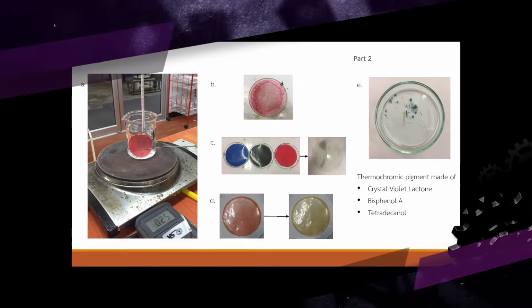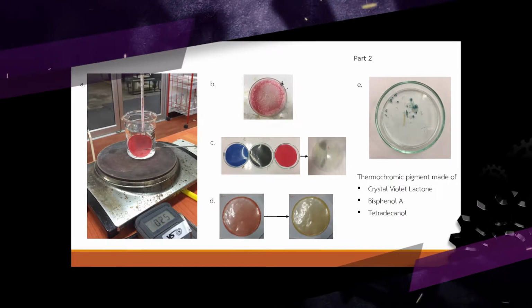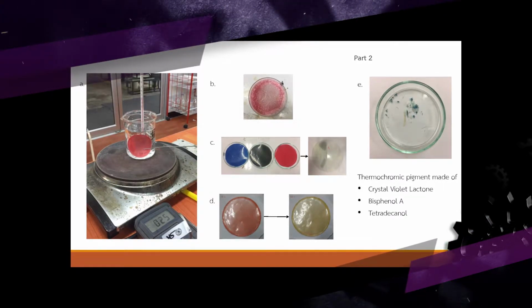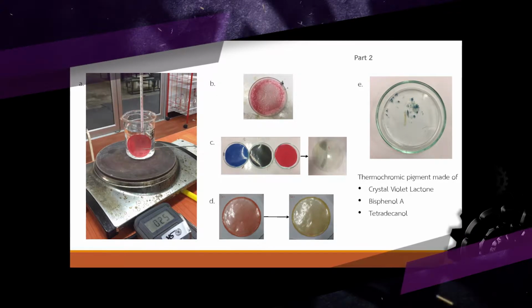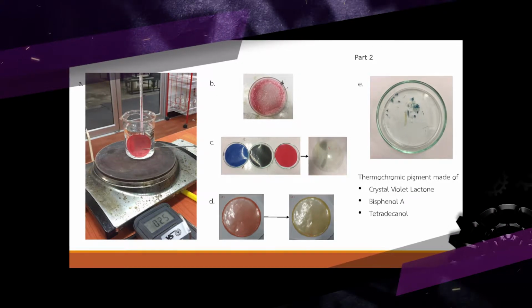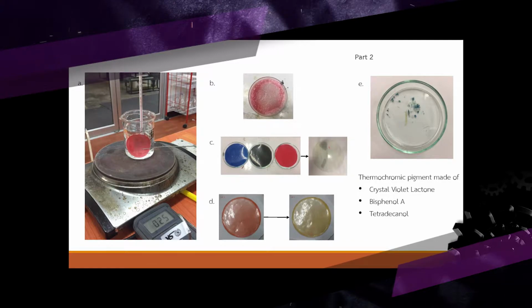We apply the ink solution into 3 different types of polymers and cast it into thin film form. Those 3 polymers are natural rubber, polyethylene glycol, and polyvinyl alcohol. Our study was separated into two parts. In part 1, we studied the reversibility of the thermochromic system by heating up the films at a constant heating rate and recording the temperature of the films and the water inside.